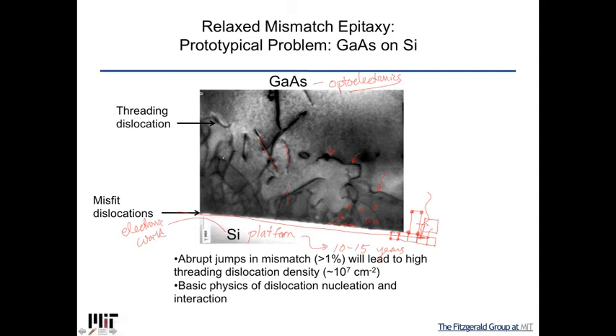this thread comes down and it has a piece in the interface which caused the relaxation. So this is the piece you actually need because it allows the gallium arsenide to relax. But because the dislocation can't end in a crystal, this has to come back up again. And so this is referred to as the misfit dislocation. These black things that come up here are called the threading dislocation, but they're often the same dislocation. It's just that the part that threads up is referred to as a thread, and the part at the interface is called the misfit dislocation.